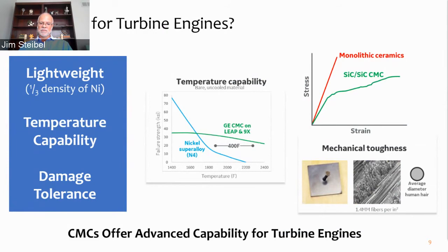You see the stress-strain response, and I think most know the brittle china and ceramics you see around the house in your everyday life has a stress-strain curve that looks like a monolithic material, shown in red, because indeed the form of the material is singular, and there is nothing there to stop cracks, as compared to a composite, which has multiple forms of material, capturing the aspects of the fibers themselves combined with the matrix.